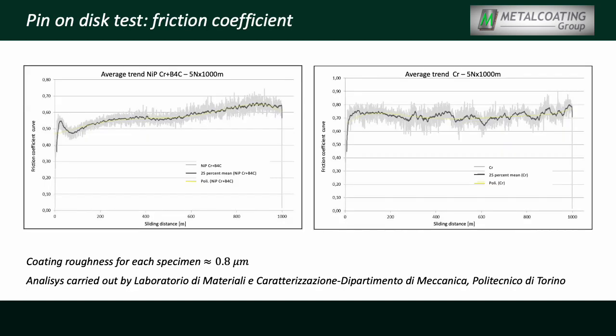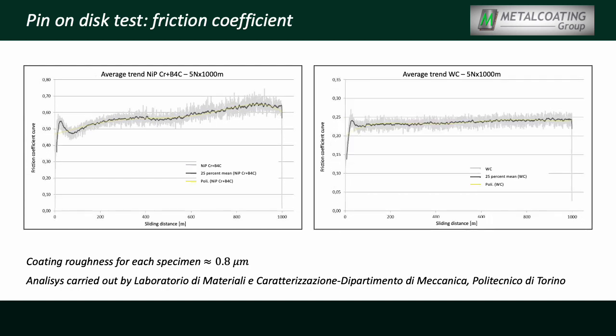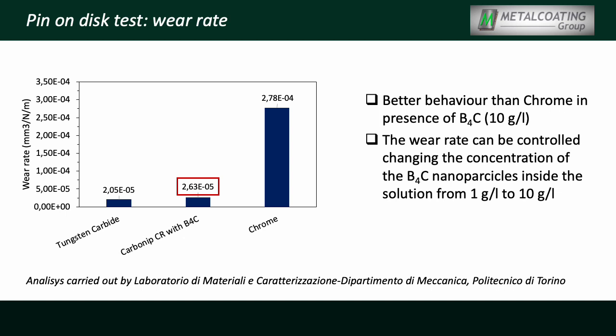Pin-on-disc test was performed to evaluate some important properties. First, the friction coefficient among Carbonip, chrome, and tungsten carbide. Tungsten carbide results could not be the real value because the pin of the instrument is made of the same material. The wear rate results show Carbonip value 10 times lower than chrome and quite close to tungsten carbide.